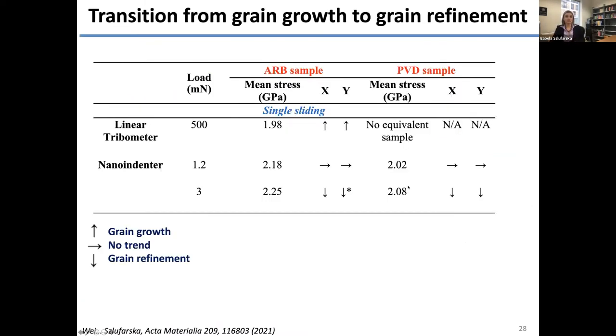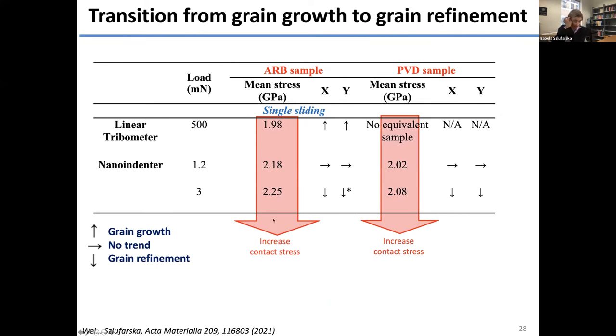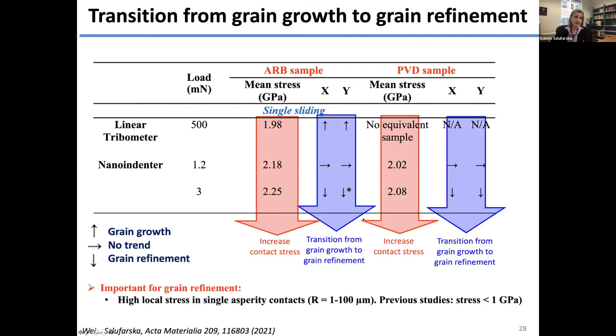Okay. So now we have also observed a transition from grain growth to grain refinement as a function of sliding conditions. And I want to tell you about this. So I'm showing you experimental results for the ARB sample and for the PVD sample. They're consistent with each other. We performed, in this case, single sliding, either with a nanoindenter, with a diamond tip, or with a tribometer. And here I'm showing how the stress increases in our experiments. The arrows mean that there's a grain growth, no trend or grain refinement. And you can see that as the stress increases, there's a transition from grain growth to no trend to grain refinement.